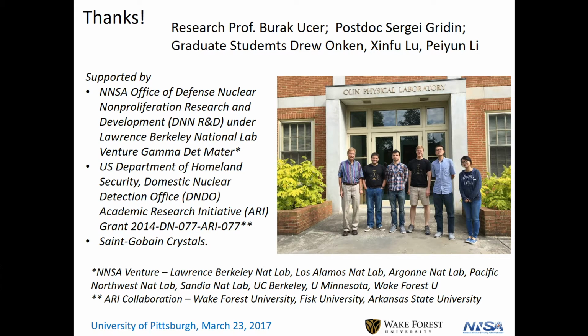Like I said, in that LHC upgrade, nobody currently thinks that you're going to get a scintillator that will decay in a picosecond, and that's kind of squarely in you guys' area. But I've worked on that too, the idea of giant oscillator strength of exciton emission and so forth. But there's a fundamental limit, Fermi's golden rule gets in your way, because, in fact, I had a student do this. I said, go to the NIST tables and find me the fastest atomic spontaneous emission that exists. Scintillation is spontaneous emission. And it was 7 nanoseconds for a beryllium charge state.